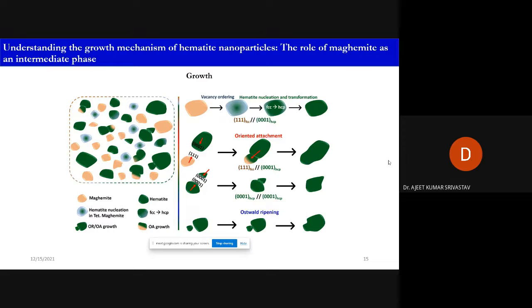They can come together, and finally you can have larger particles of hematite. And if you have two hematite particles, their basal planes can come together, and that is how you can form bigger hematite particles. But at the same time, through Ostwald ripening, larger particles eat away the smaller particles, and that is how they become bigger.